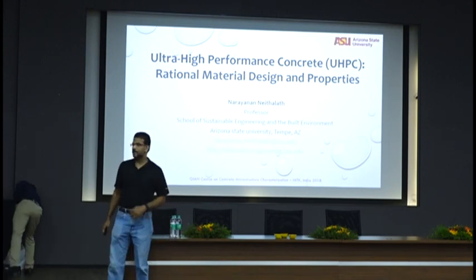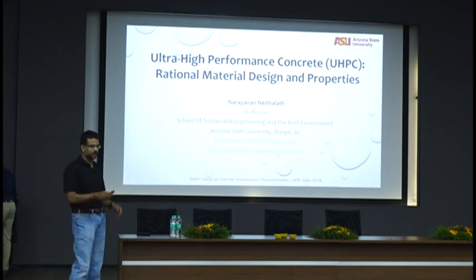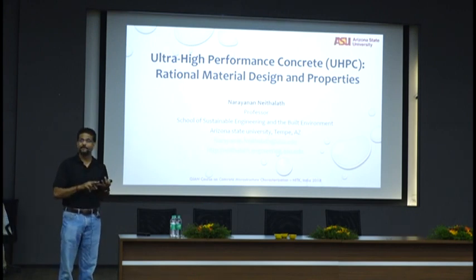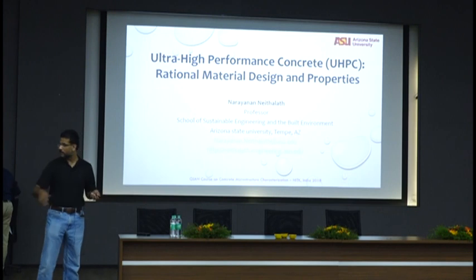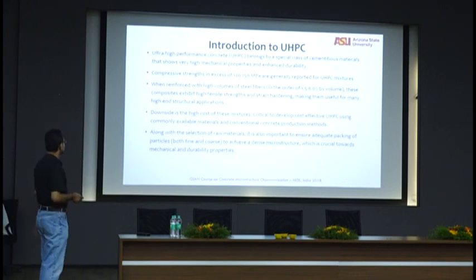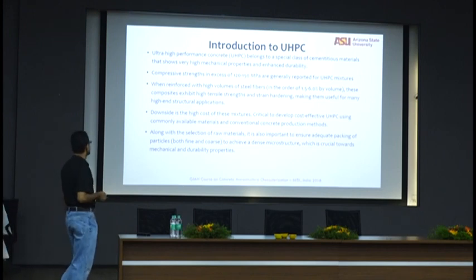So we developed something for a fraction. We developed our own ultra high performance concrete for about $500 a cubic yard. So 1/6 of the cost of Ductal, without using any of that fancy materials like quartz powder and this and that. We used only locally available materials and the whole idea based on what I talked about in the morning on particle packing. Okay, so UHPC about 120 to 150 MPa strength.